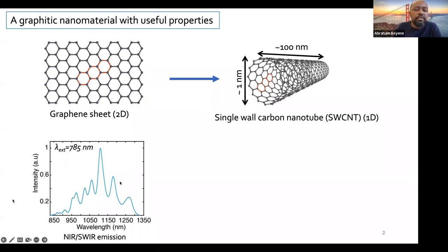The reason you see these differences in peaks and this fairly complex looking fluorescence emission spectrum is because photo emission from nanotubes is highly sensitive to the geometry of the wrapping of the graphene, such that slight differences in diameter have a very profound effect on the electronic band gap structure that then translates into these slight differences in photo emission. So the takeaway is that this is a fairly complex looking fluorescence emission spectrum, because we have multiple nanotubes all confined within this window.